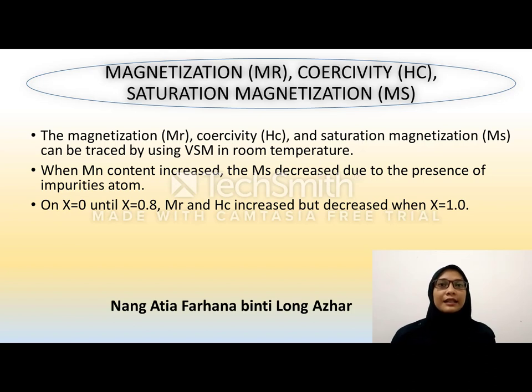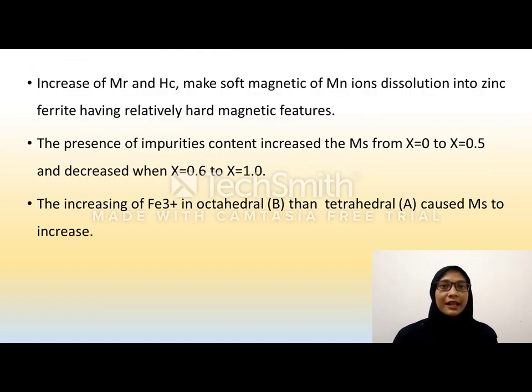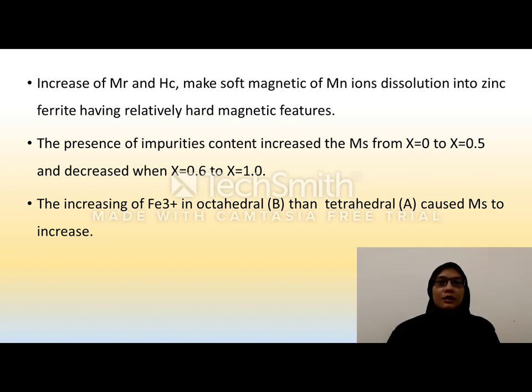When manganese content increases, the saturation magnetization decreases due to the presence of impurity atoms. From X equals 0 until X equals 0.8, magnetization and coercivity increase but decrease when X equals 1.0. The increase of magnetization and coercivity makes soft magnetic manganese ion dissolution into zinc ferrite have relatively hard magnetic features. The presence of impurities increases the saturation magnetization from X equals 0 until X equals 0.5 and decreases from X equals 0.6 until X equals 1.0.